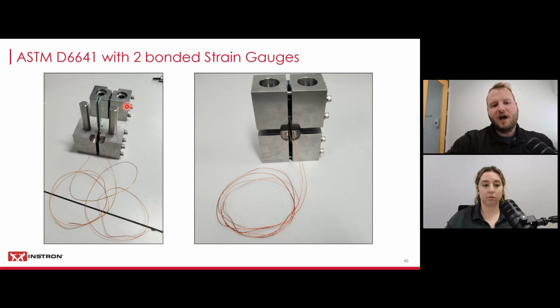And then you put the upper half on there, and you need to torque these screws here on the side to bring in the sufficient shear loading into your specimen. So you need to make sure that the ends are flush here for the end loading part, right? So you're going to have the specimen here in the first part sit down on the flat surface, and then you need to make sure on the top, when you flip it all around and put this part into the other one, that you again get that nice flush bottom where the specimen and the fixture are nice and even.